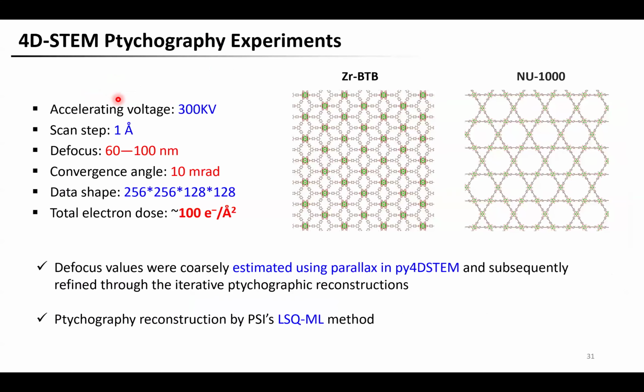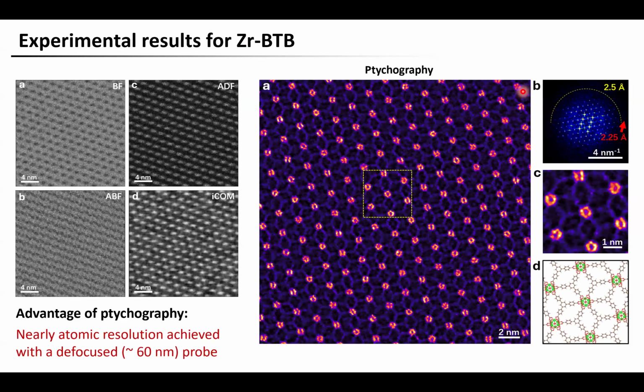Using the optimal conditions identified through simulation, we conducted 4D STEM experiments on two MOFs, zirconium BTB and NU1000. And the results are quite encouraging. As you can see here, we have successfully reconstructed the ptychography image for zirconium BTB with a resolution close to 2 angstrom using a 60 nanometer defocused probe. Because the probe was defocused, the conventional STEM image collected using the same probe is of poor resolution, right? And this demonstrates the advantage of electron ptychography discussed earlier.